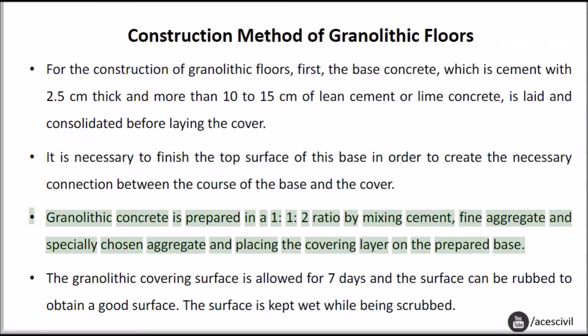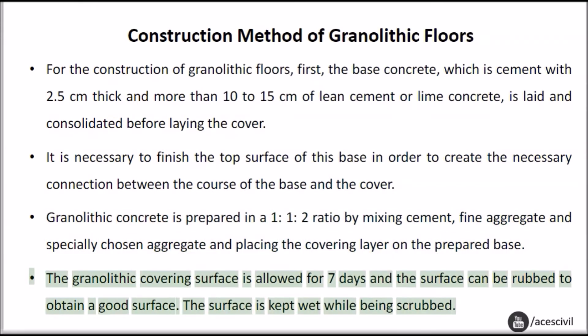Granolithic concrete is prepared in a 1:1:2 ratio by mixing cement, fine aggregate and specially chosen aggregate, and placing the covering layer on the prepared base. The granolithic covering surface is allowed to cure for 7 days, and the surface can be rubbed to obtain a good finish. The surface is kept wet while being scrubbed.